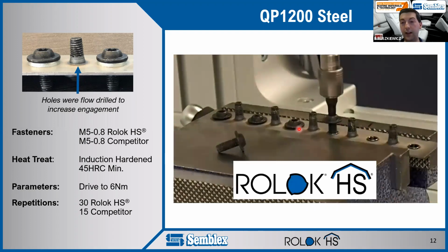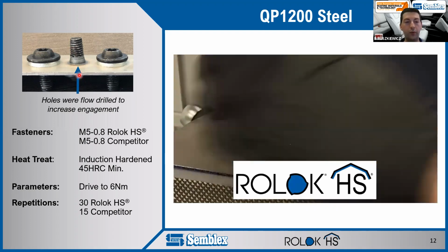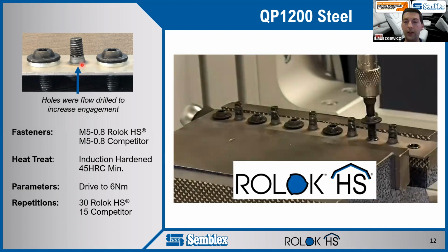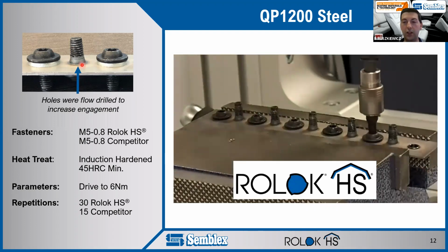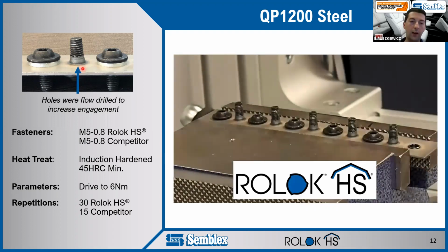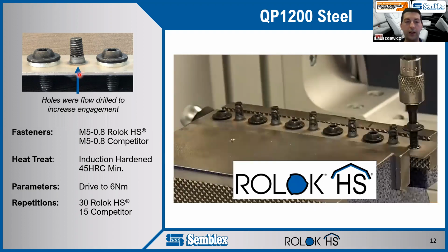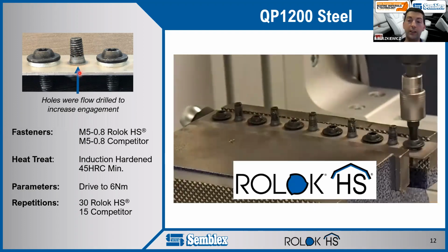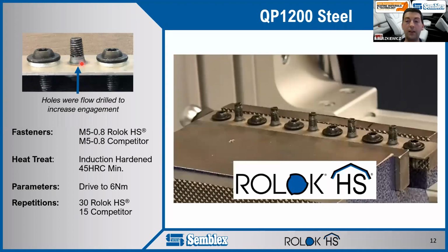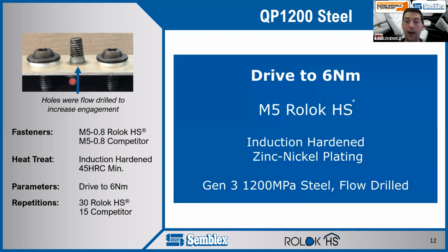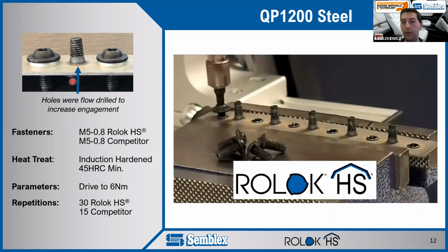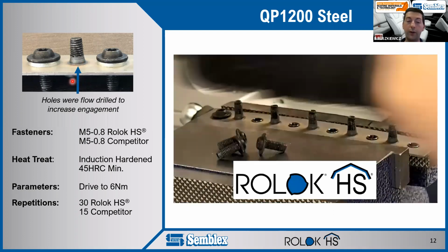But because this steel is thin, we had to flow drill an extrusion, which you can see in this picture on the top left, to give us enough length of engagement for our M5 screw. The steel is only 1.2 millimeters thick, so we used a carbide flow drill, which is a separate operation. The screw does not make this extrusion. Then we drove the screws into that extruded hole. We did check the hardness before and after, and we were within 2 points of the original on the Rockwell C scale, so we still had about the same strength, right around 1200.